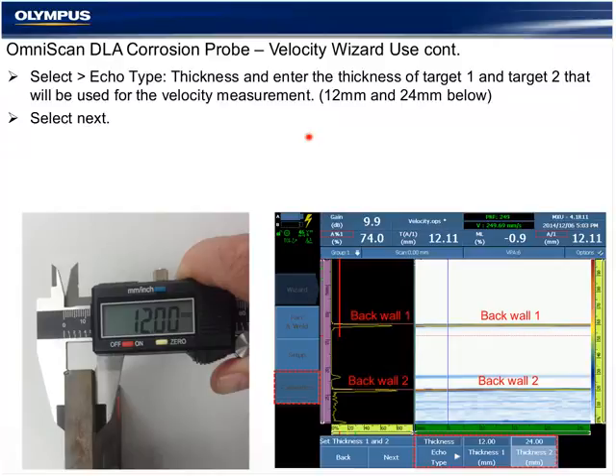So in cases where we do actually have to change the velocity, duplex, we're starting to see more exotic materials that are requiring inspection. Keep in mind that this probe is a 7.5 megahertz probe, so that's optimized for carbon steel. More attenuative austenitic materials might require a different frequency of probe.